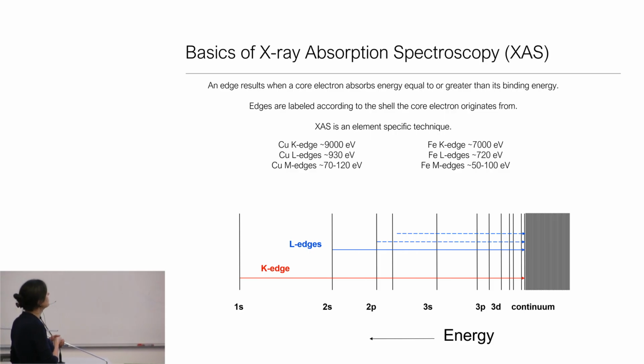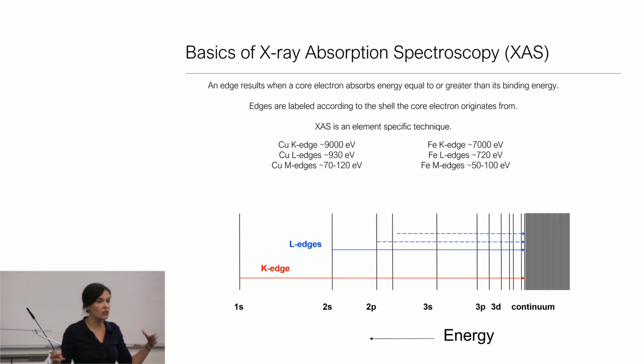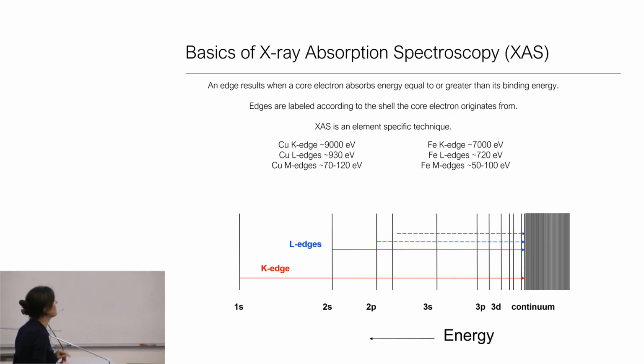For copper, that happens at around 9,000 electron volts for a 1s electron. For iron, that happens at around 7,000 electron volts. So these events are separated by 2,000 eV. It means if I have a complex system, I can very separately look at the copper and look at the iron. In many spectroscopies, if they're both paramagnetic or if they're both optically active, these things overlap. So I would say this is one of the biggest strengths of X-ray spectroscopy: its element selectivity.